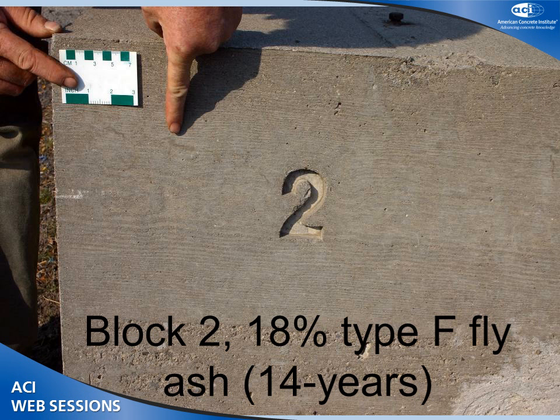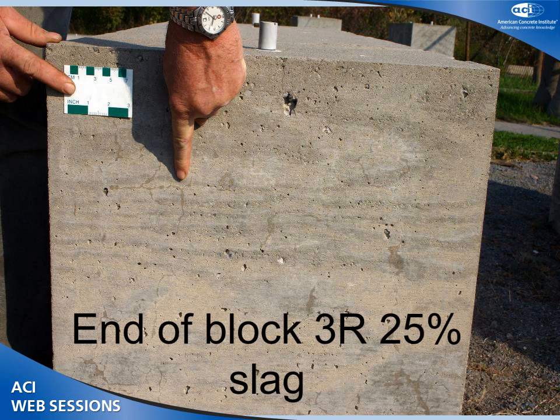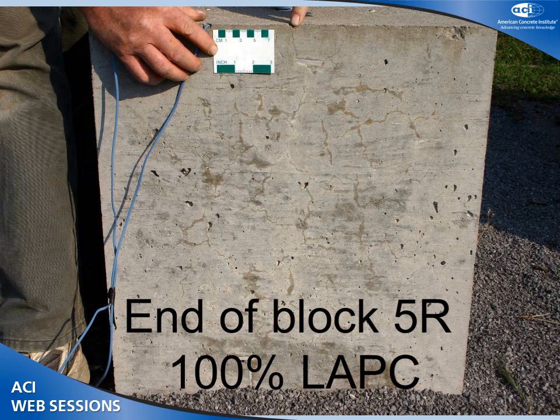And just to show you the sort of cracking, this is after 14 years. There's the 18% fly ash. We started to see minor cracking on the side of the beam. And again, with the 25% slag, you can see minor cracking. With the low-alkali cement, you see a more extensive crack pattern. So the low-alkali cement is not mitigating.